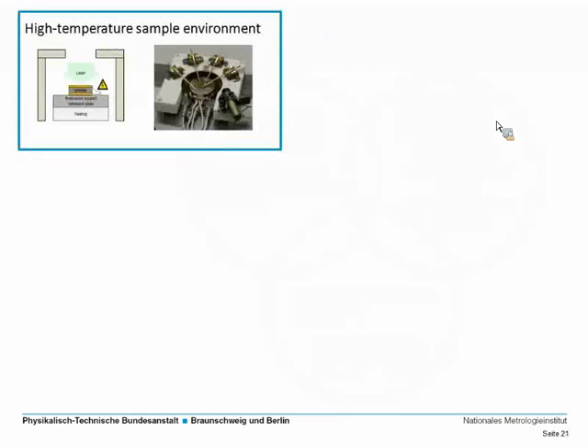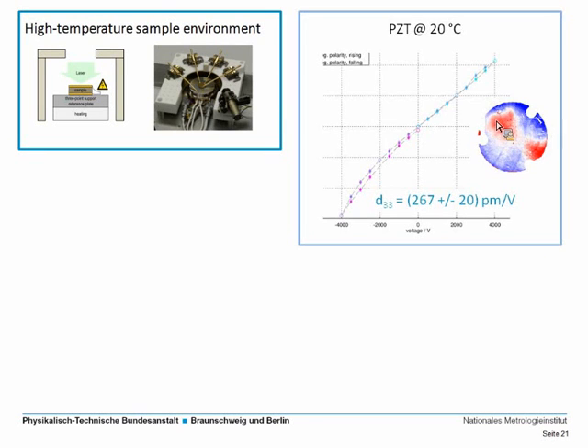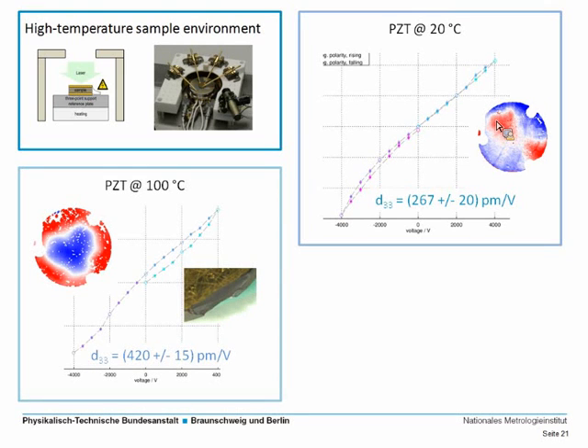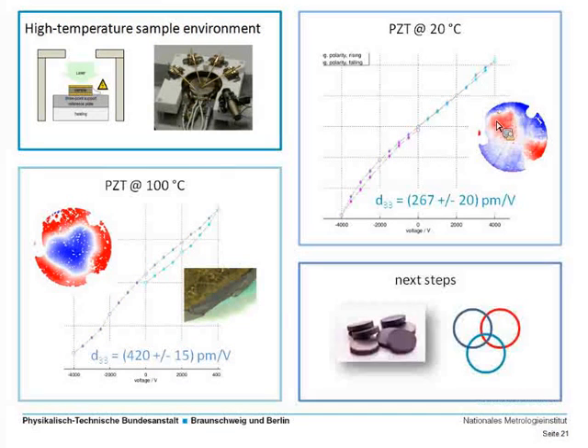And with that, I would like to conclude. I introduced you to our high-temperature sample environment to do interferometric length measurements on high-temperature piezoelectric materials. I showed you some results for PZT at room temperature, for PZT at higher temperature, where we saw this unexpected breakdown of the sample. I gave you a bit of a glimpse on what's next, like other materials and comparison between interferometric systems.